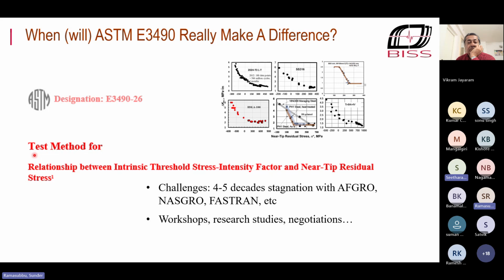As long as you account for crack closure, you're going to first get the driving force. The driving force is K max minus K opening. So you're going to first determine K opening. Then at K opening, you're going to compute sigma star. For that computation, you can use the equations that are readily available. They are applied mechanics. The stress state doesn't figure in them.